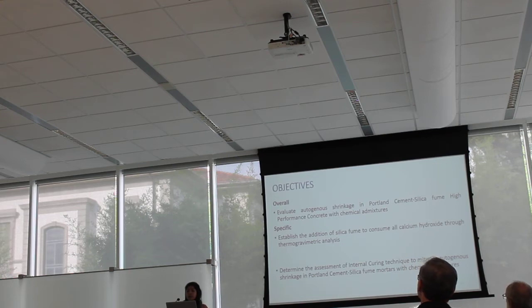We aim to determine the assessment of the internal curing technique to mitigate autogenous shrinkage in Portland cement silica fume mortars with chemical admixtures. We have to know if the chemical admixture is going to influence the autogenous shrinkage in a bad or in a good way.